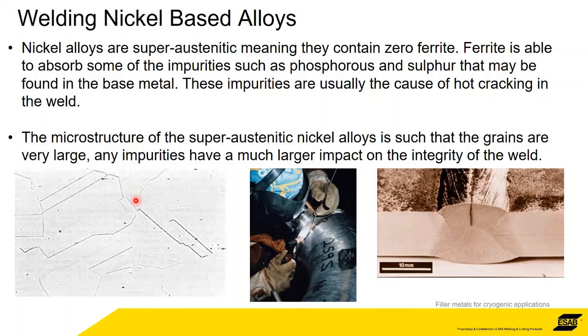What ferrite does is absorb some of any impurities that are within the steel. So you can have a very pure, very high quality filler metal, but in the base metal there may be some kind of impurities, and it's usually either phosphorus or sulfur.